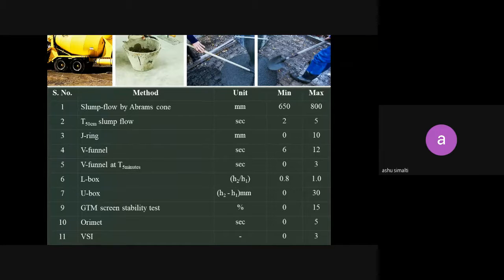These are the limits prescribed by different codes for those test values. Slump flow by Abrams cone, unit is mm, minimum 650, maximum 800. T50 centimeter slump flow, measured in seconds, minimum 2 seconds, maximum 5. J ring, again mm, minimum 0, maximum 10. If it exceeds 10, it has to be repeated. V funnel, again seconds, minimum 6, maximum 12. V funnel at 5 minutes, 0 to 3.